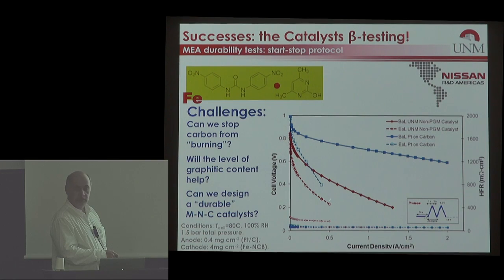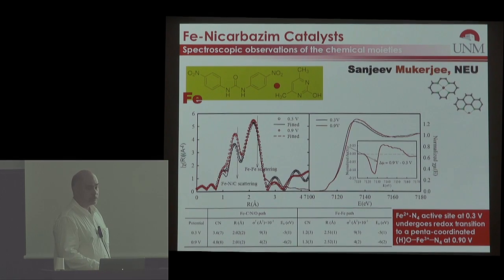Arguably, our catalyst burns less. But here you start from an excellent catalyst and end with a bad catalyst. Here you start with a bad catalyst and end with a very poor one. So that is the difference. The reality is that any carbonaceous catalyst that has a carbonaceous support or carbonaceous backbone or matrix will decompose, or essentially oxidize, under those conditions. Hence, I think that system-level solutions are needed to mitigate the start and stop problems of the fuel cells. And those are available. They are just expensive.